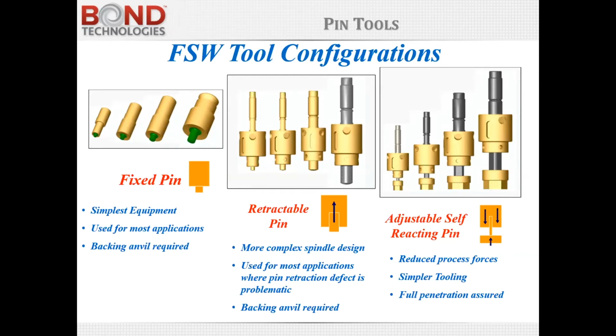One of the benefits you can get from this is when you finish a weld, the pin can gradually retract over the last several millimeters of the weld to eliminate the exit hole that may be present with a fixed pin. The downside is that it does require an additional axis, and the equipment cost can go up, and it's a little specialized. But if you have an additional axis, you can also do the pin configuration on the right, which is an adjustable self-reacting pin.